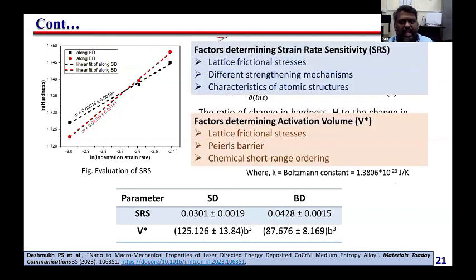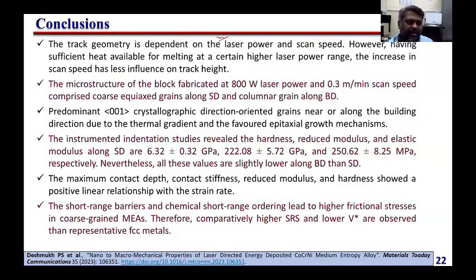Mainly these factors contribute to this. We determined this from the outcome of strain rate sensitivity and activation volume. The chemical short range ordering in this alloy plays a very important role, along with the Peierls barrier and lattice friction stress. These are all playing an important role, which is why we get a very low activation volume.